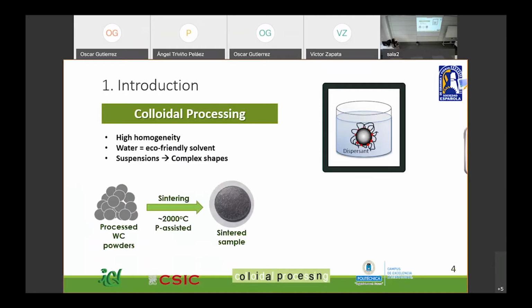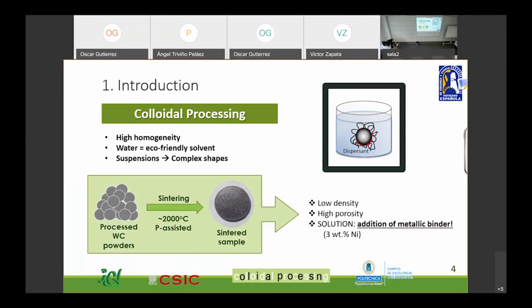Traditionally, tungsten carbide materials have been sintered under really extreme conditions, and actually the results weren't that good in terms of density or porosity. So the solution in this case would be the addition of a metallic binder. In our project, we decided to use 3% in weight of nickel.